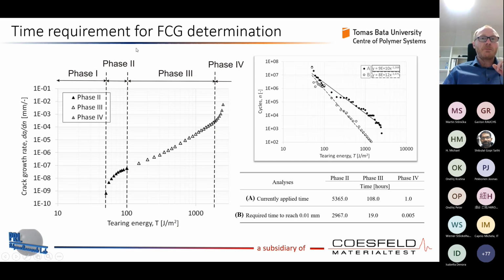A very important question is the time requirement for the fatigue crack growth determination. You can see here for this EPDM with fill fraction 0.24, there is a right-hand side diagram, which is the dependence of tearing energy on the cycle number. How many cycles we needed for the measurement of this tearing energy of the crack propagation. There are two data sets, A and B, whereas A is the currently applied time, that means what we really applied, and B is the recalculated time to reach the crack growth of 0.01 millimeter, 10 microns, because 10 microns would be enough for the optical system of the tyre fatigue analyzer to detect there is a stable crack growth.